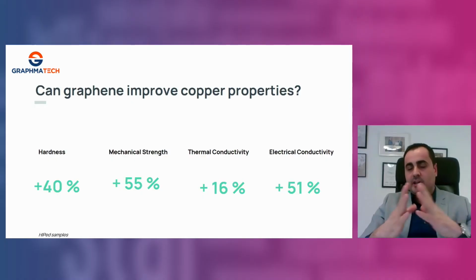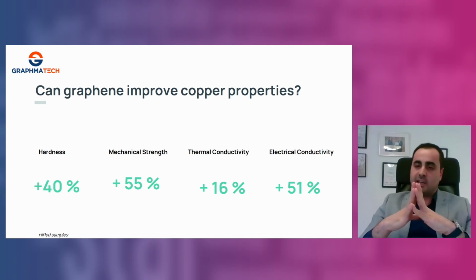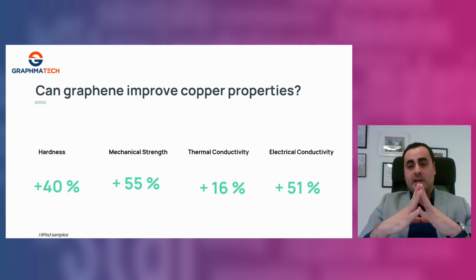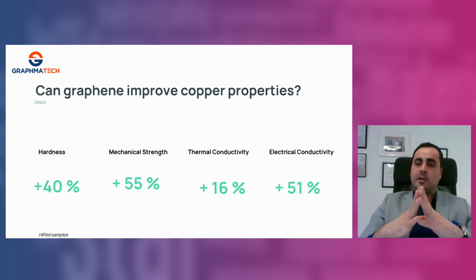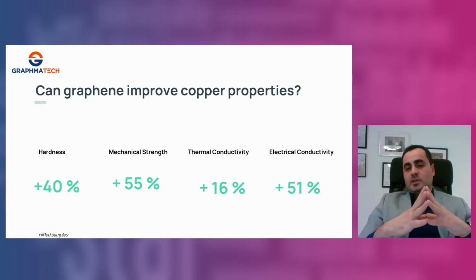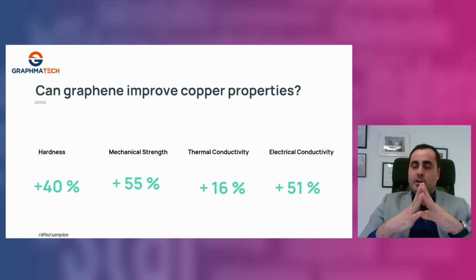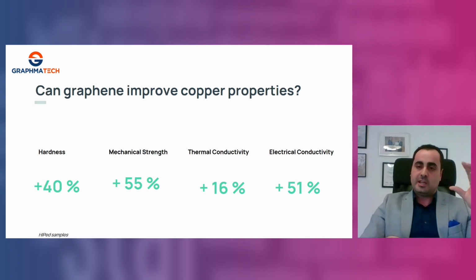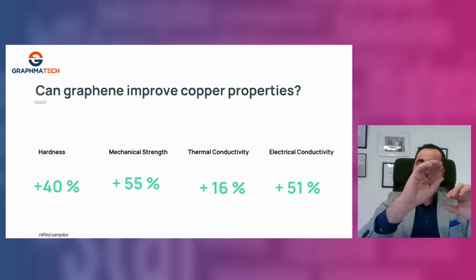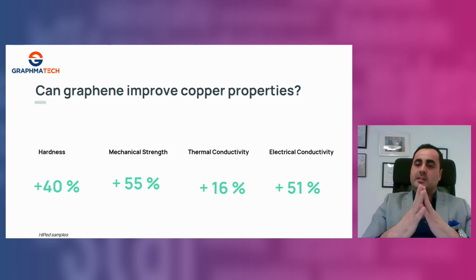So you might ask, can graphene improve the copper properties? Here I don't tell much, but I can tell you in general, yes. In another project where I am not able to talk that much, we measured improvement in the copper when we added a low concentration of graphene. Improvement has been even in the thermal and electrical conductivities. So with this, there is a huge potential that yes, we can make copper even greater to enable the use of much less copper and to duplicate this work on other metals to make them even exceed copper in properties and to replace it in the future.